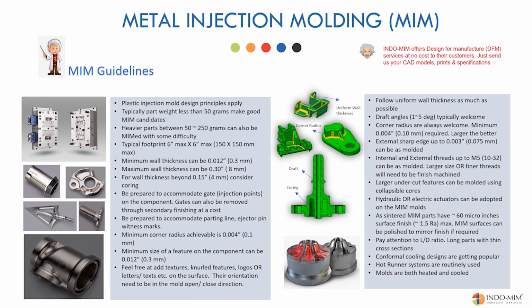When you consider MIM as the production process for a component, be prepared to accept gate and ejector pin witness marks on the component. Large corner radius, uniform wall thickness are all considered as good design attributes. Draft angles, where possible, are good for molding. Minimum wall thickness should be 0.30 millimeters or 0.012 inches. Maximum wall thickness can be 8 millimeters or 0.30 inches. I would say the sweet spot is between 2 and 4 millimeters. Internal and external threads up to 6 millimeters in size or 0.25 inches can be easily molded.